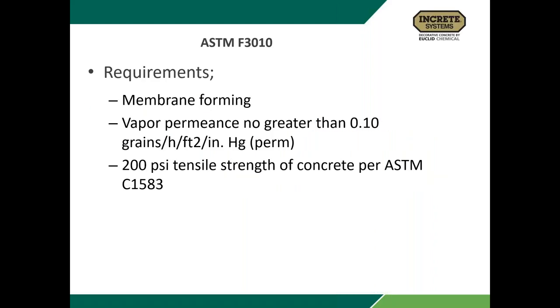It requires, one, that it be membrane forming. It has to form a membrane on the surface to stop the vapor from passing through. It gives a permeance of no greater than 0.1 perms. Basically, that's a perm rating that's very, very low. It's actually quantifying how much vapor is allowed to pass through that coating. And it calls for a minimum 200 PSI tensile strength of the concrete itself. The reason being that if I don't have that 200 PSI tensile strength and I put on a coating that wants to hold the vapor in and is bonded really well to the concrete, it'll pull the concrete apart. So we want to actually test the concrete and make sure that the tensile strength is there.